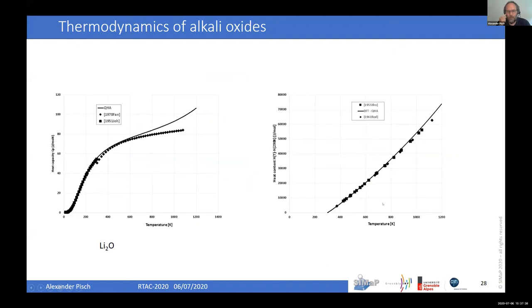There is not much data in the literature. This is because it's very, very complicated to measure. Here is one example, the one for lithium oxide, and the value calculated by DFT phonon is given here. And you see the agreement at low temperature is very good, and we have some discrepancy starting from 600. And because the melting point is around 1100, it's clear that the DFT phonon calculations are only good up to 500-600 K.